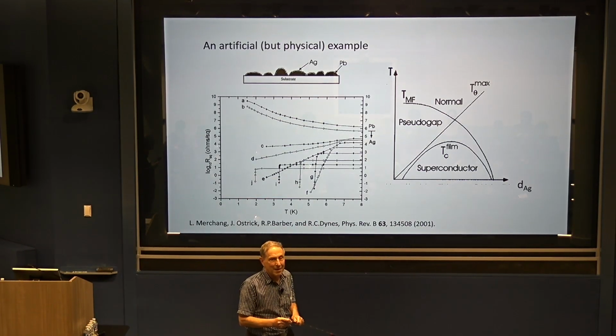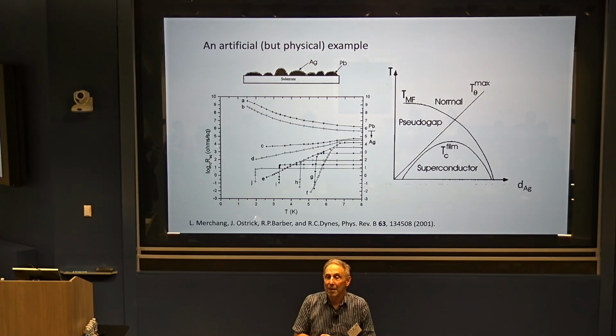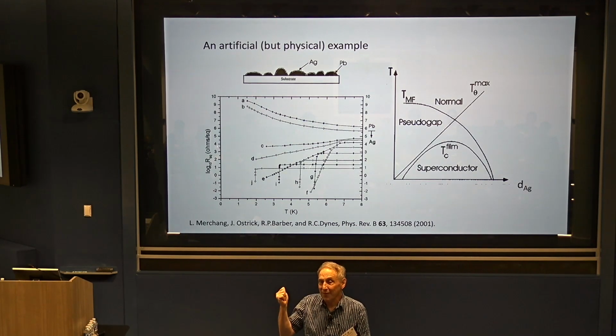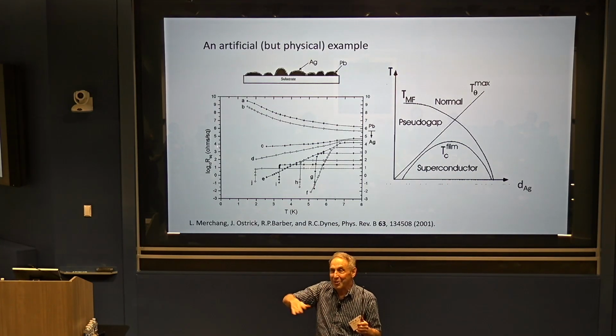So you basically want large superfluid stiffness for one material and large gap for the other layer. Is it clear that the largest superfluid stiffness in nature is in a cuprate? No, it isn't known to us. No. Of course, the reason it's obvious that phase fluctuations are important in the cuprates is they've got lower electron density. They're larger rs to start with than almost any metal. So why does the bilayer need to be two cuprate layers? It doesn't. It would be better to have it be silver or something.